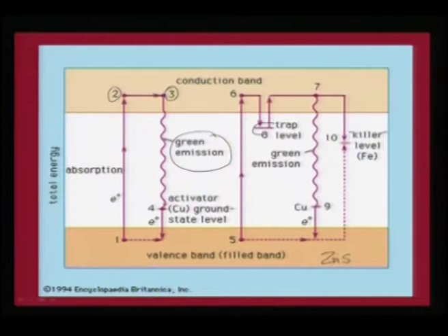There are other things that are also accompanied with it because of several processing issues. One is, if it is a defect induced one, then the electron gets trapped momentarily in this trap level, and because of the influence of the cathode ray, they do get ejected out and finally they return giving a green emission. So, there are trap levels, and the number of trap densities or trap levels do control the quantum efficiency and the purity to some extent.